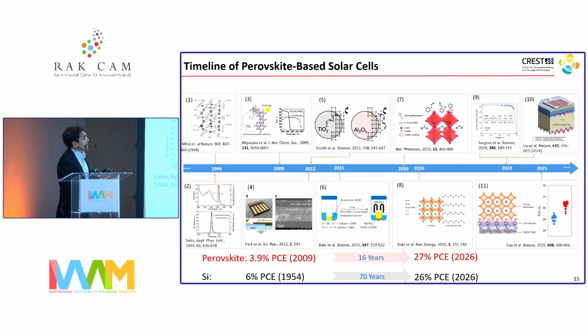And now, as we speak, perovskites as single junction devices have reached 27%, but now we see the big opportunities in tandem cells where you could create multiple layers of perovskites or combine perovskites with silicon to get devices that reach between 30 to 35% efficiency with a potential limit of 40%.